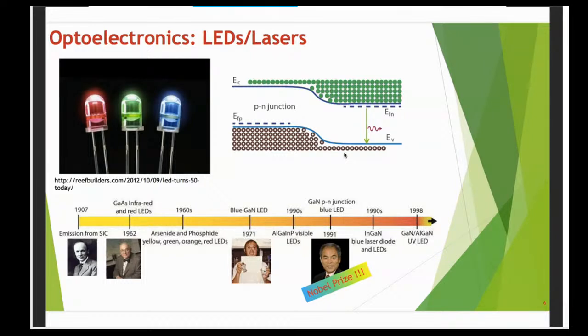The relation between band gap and the wavelength of emission is that the higher the band gap, the lower the emission wavelength that you can get. So for that, we needed a gallium nitride LED, which could allow blue emission, which is around 400 nanometers or so. In the 1970s, work started with the first demonstration of a GaN LED, which I heard is still working even now, if you put current across it, stored in some university lab.